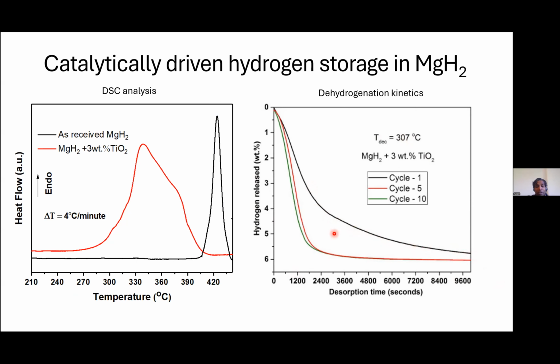But what is interesting is when you repeatedly do it, the kinetics and capacity both increase. In 5 cycles, it reaches a maximum, and after that, it stays. What does it suggest? It suggests that there could be a chemical reaction between titanium dioxide and magnesium hydride that might have produced an active species. That active species promotes further cycles.